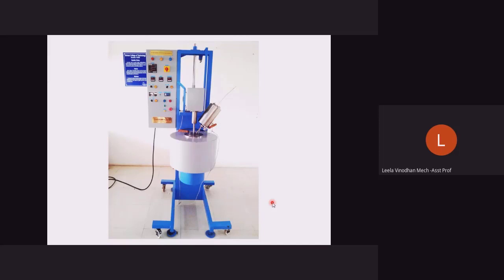So I request everyone to maintain the magnesium inside the crucible for quite a bit of time. Within that time, as soon as you add the reinforcement into the magnesium material, allow the material to pour down and then take the casting. The privilege of having more time with the aluminum is not available for the magnesium. That we have to be very careful.